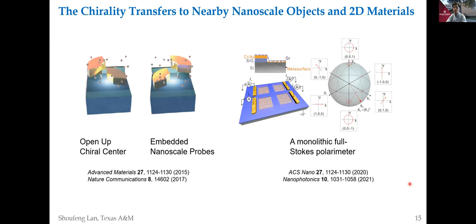And more interestingly, this chirality from those nanostructures can be coupled to nearby objects, such as quantum dots and 2D materials. For the quantum dots, we observed circularly polarized emission, which otherwise would not be possible. And for the 2D materials, in this case graphene, we can separate, analyze, and detect the full Stokes polarization of light on a monolithic device.